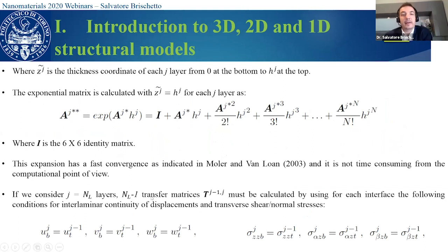And finally, the last condition is, if you remember, the equations are written for each layer, and we use a layer-wise approach, which means that we write the equations separately for each layer, okay? And then we need to connect the layers between them. We have the problem at each interface in order to impose the continuity conditions, because we use a layer-wise approach. This is important because, thanks to the layer-wise approach, we can obtain very refined results, okay? How to impose these interlaminar conditions?